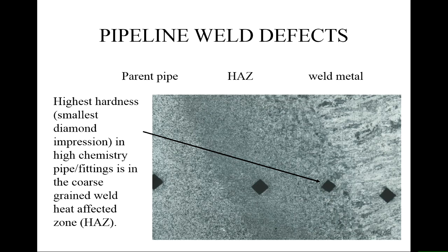But in this part of the heat affected zone, right next to the weld bead, that impression is smaller, so that has a higher hardness. And this is where phases like martensite form, and this is where brittleness is most likely to occur. So you will most likely see cracks, if you do get them in welding, in the heat affected zone next to the weld pool. Well, that's where they'll start.